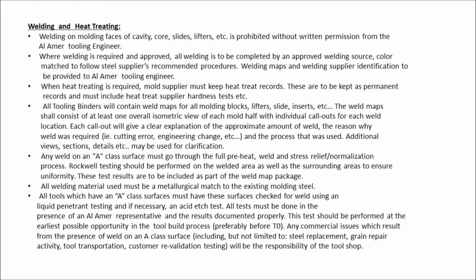All tools which have A-class surfaces must have these surfaces checked for weld using liquid penetrant testing and, if necessary, an acid etch test. All tests must be done in the presence of an Al Amer representative and the results documented properly. This test should be performed at the earliest possible opportunity in the tool build process, preferably before T0.